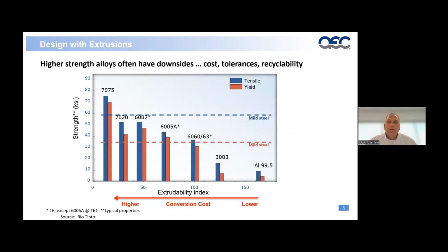So the foundation that we tend to work from here is this chart. When we look, as I talked before, we get into 7000 series as we go up in tensile and yield with the 7000 series, and then we come down the chart from 6082, 6005 all the way down to 3003. You can see we fall off on strength, but if you look at the bottom on the extrudability index, that lower strength tends to drive a lower cost for extrusion. So what we want to do ideally is we want the lower cost extrudability or the enhanced extrudability of an alloy, but get the product performance needs met with a specific chemistry. And that's what we're going to talk a little bit further about.